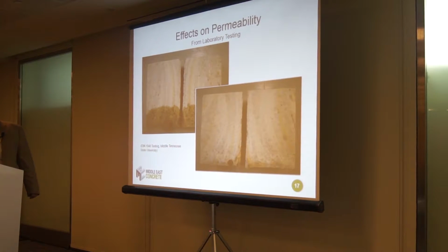And this test here, let's see if I can figure out the pointer. This is a penny, US penny. This test here was stopped after only 20 minutes because the water was going through the concrete sample so quickly that they shut the test down. This was 72 hours, same concrete, the only difference being that this was treated with spray applied colloidal nanosilica. At 72 hours, there was only about 5 millimeters penetration into the concrete. That's a pretty significant change in how that concrete was behaving.